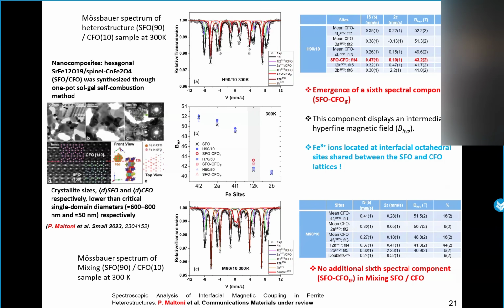It is enough to have a qualitative description, because we observe some changes in different hyperfine parameters. But for the site 12K, we observe some broadening of the lines. So it's not possible to reproduce the 12K using just one subspectrum. We have to add an additional subspectrum, and so we observe the emergence of a sixth spectral component. The hyperfine parameters of this subspectrum are between the hyperfine parameters of the 12K of strontium hexaferrite and the octahedral and tetrahedral sites of cobalt ferrite. So we attributed this subspectrum to the iron 3+ ions located at the interfacial octahedral site shared between SFO and CFO.